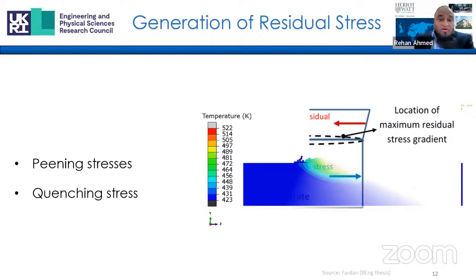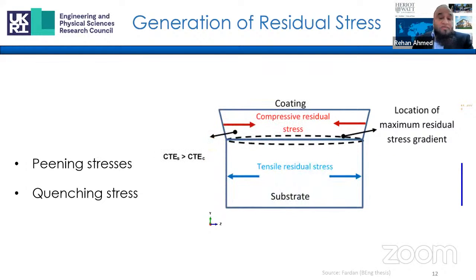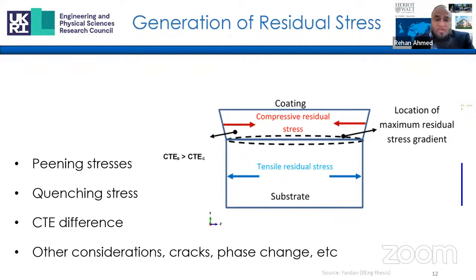Thermal stresses, on the other hand, are caused due to the difference in the coefficient of thermal expansion of the coating and substrate materials, and these stresses can be tensile or compressive depending upon the mismatch of the coefficient of thermal expansion. So for example, a compressive residual stress will be formed in the coating and tensile in the substrate if the coefficient of thermal expansion of the substrate is greater than that of the coating. Other considerations when we are looking at the generation of residual stress are the cracks and phase transformations and post-treatment which has been applied to the coating. So all of these factors influence the overall residual stress profile.